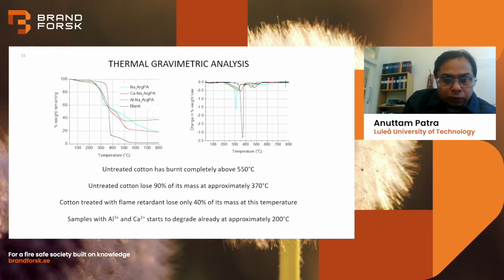We also tested all the samples with thermogravimetric analysis. I will not show all, but for this, our final mixture, I will show. For the black one, the untreated cotton, it can withstand heat quite high. At the beginning, till 350, there is nothing, but then it catches fire and it loses almost all the material. Above 550 degrees, it's almost gone. At 370, almost 85 to 90% is gone, but at the same temperature, the treated clothes lose around only 40% of the weight. So that is good. And also for these calcium and aluminium samples, they started decomposing at 200 degrees, a bit lower. So the flame retardant behavior already started at that temperature. So that is also quite impressive.